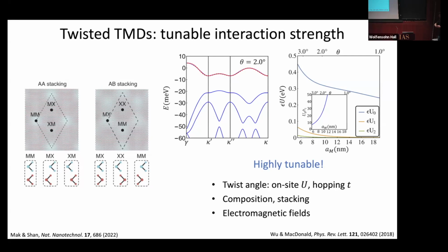Both of these, as you make your Moiré wavelength larger and larger, tend to go down. But the hopping goes down exponentially as you increase the Moiré wavelength, whereas the on-site interaction decreases more slowly. And so what that means is by tuning the twist angle and the Moiré wavelength, you can tune the ratio of the on-site repulsion U to the hopping t over quite a large range. Shown here is nearly an order of magnitude.